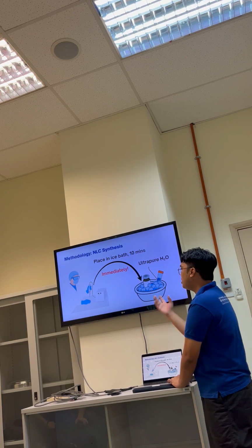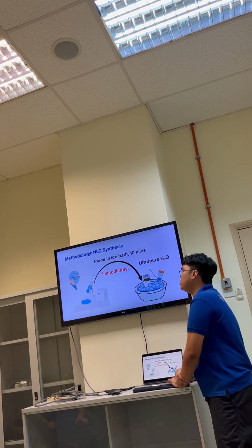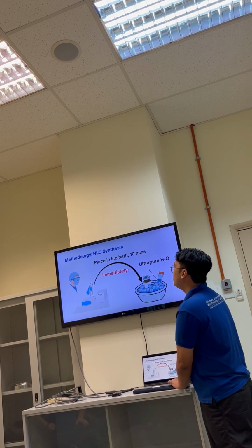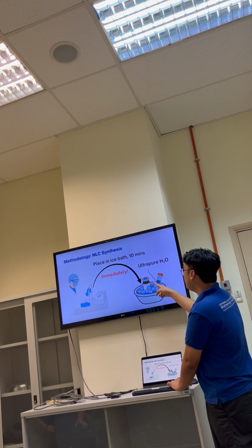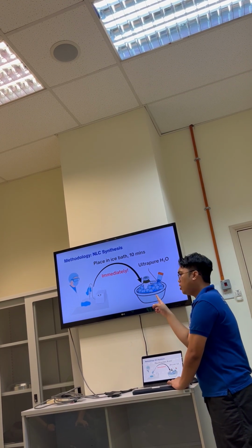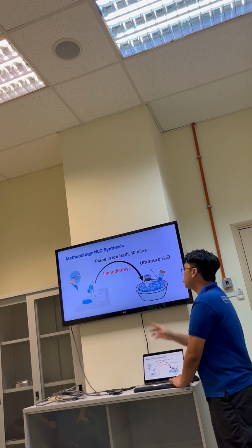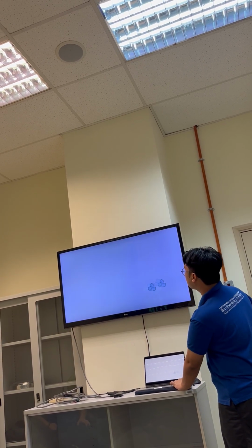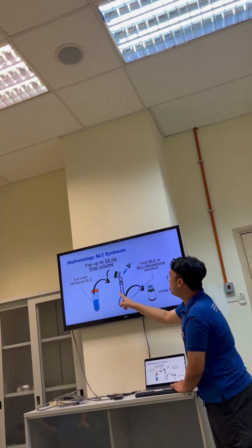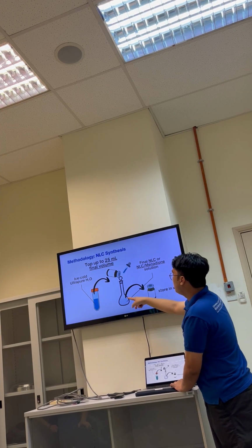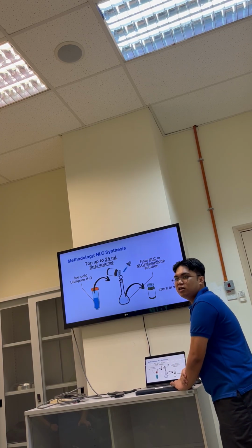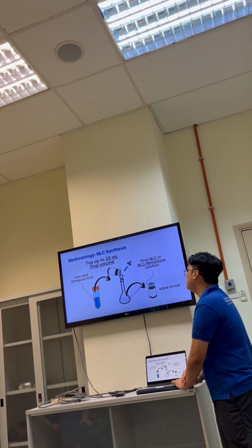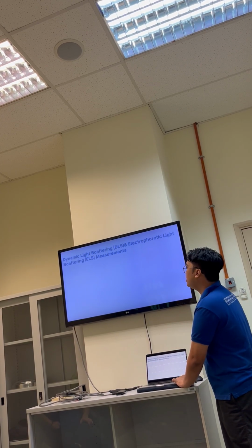So we just want that imperfect form of our lipid matrix. And how to do so? We quench the recrystallization kinetics right away using the cold solution here, or ice bath solution here. Then finally, we just top up our NLC solution to the appropriate volume so we can get the final drug-loaded NLC solution. And of course, store it in the vial.